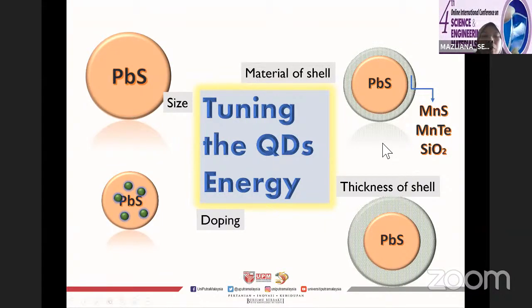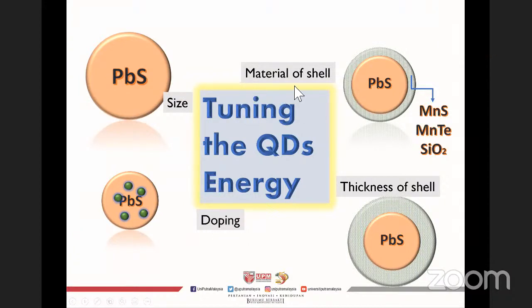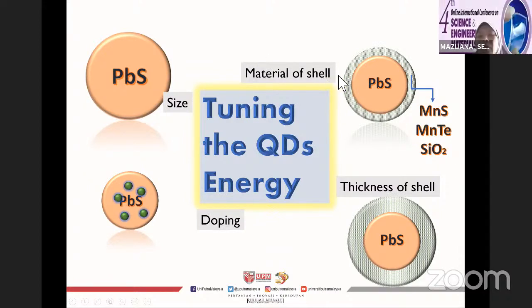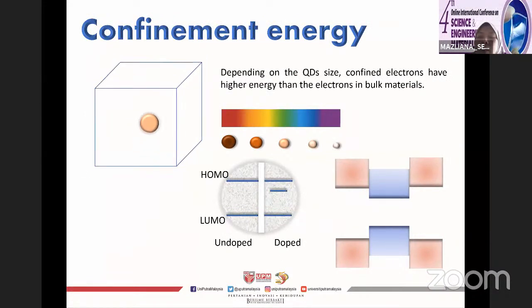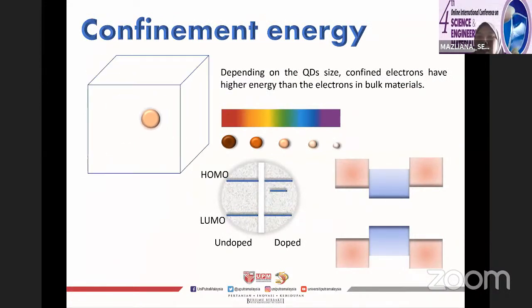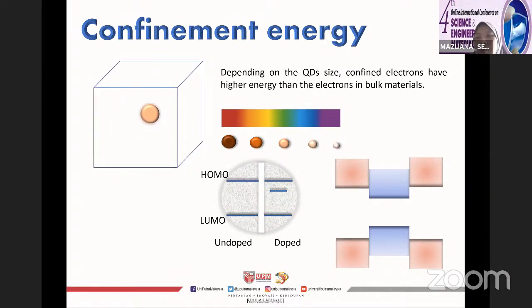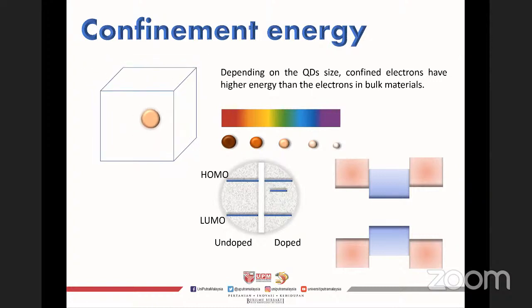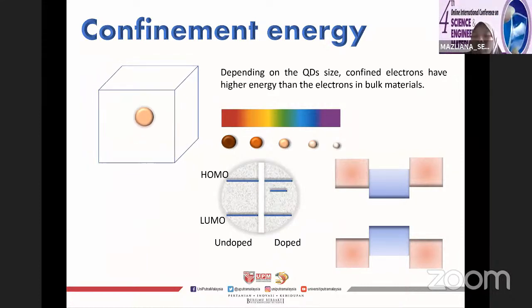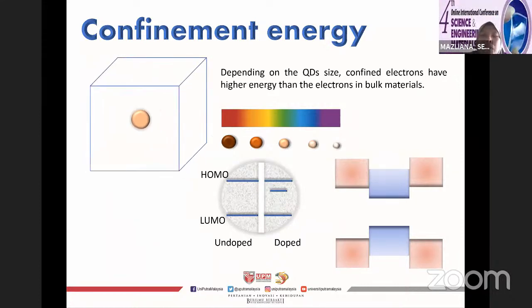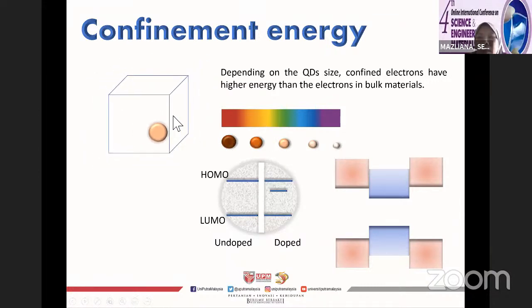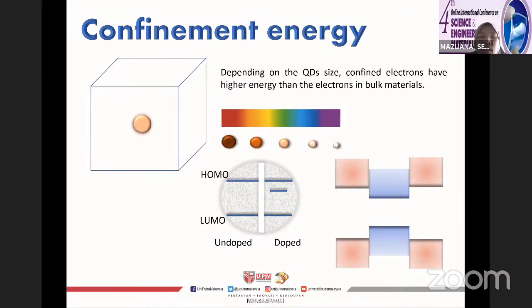So in summary, if you would like to tune the quantum dot energy, we can change the size, we can dope the quantum dots, we can put a shell layer so it will form a core-shell structure, or we can change the thickness of the shell. So whichever approach we choose, what we actually did was change the confinement energy. This phenomenon of raising the exciton energy by reducing the crystallite size is known as quantum confinement. It is known as quantum confinement because, as you can see in the animation here, when I reduce the size of the box, the carrier is restricted in the small box.